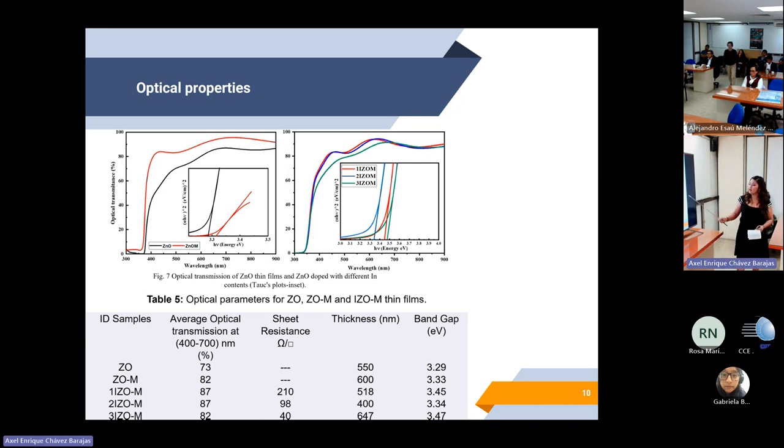In this figure, we can see indium at different contents. We observe the optical transmission decreases with increased indium content. The band gap in general increases with increased indium content, which is attributed to the well-known Moss-Burstein effect.